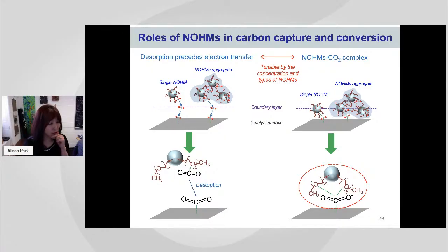If that's the case, our Faraday efficiencies should be very similar to the regular electrolyte system. But what we also found out was we do have a slight difference in Faraday efficiency. That means we have another mechanism. So if you look at the right-hand side, we actually have CO2 being delivered by NOHMs to the surface. During the adsorption of CO2 on the surface of the catalyst, NOHMs is hovering around, and depending on the binding energy, even without the strong interaction, you can bend the CO2 just right to change the reaction pathways of that adsorbed CO2. So even with the same catalyst, you will end up with different products.